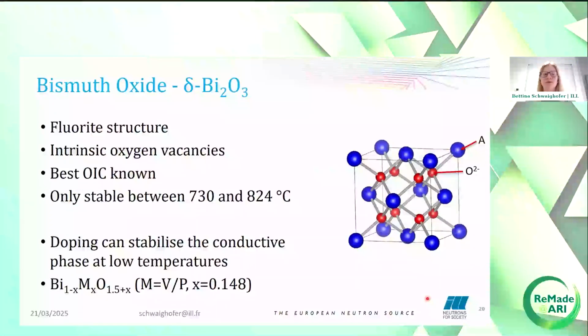The best oxide-ion conductor we currently know is the delta phase of bismuth oxide. It adopts a fluorite crystal structure with intrinsic oxygen vacancies. The fluorite structure you can see here, but only 3/4 of the tetrahedral holes are occupied by oxide ions. This leads to the very high ionic conductivity, but unfortunately the delta phase is only stable in a very narrow temperature range. However, we can stabilize the high temperature phase at low temperatures through doping.